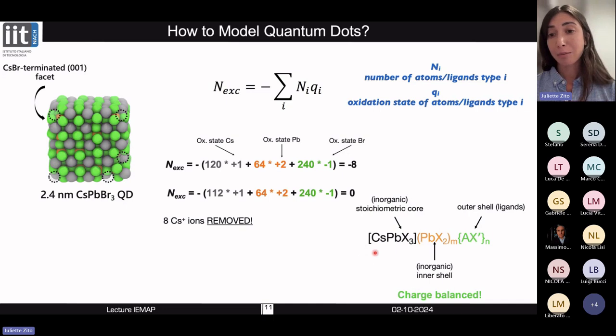and with our final quantum dot model that can be written as made of an inorganic stoichiometric core with an inner shell, surface shell, which is still inorganic, and then an outer surface shell, which in our model is inorganic, so A is cesium and X is bromide. But in the experiments, A can be a cationic ligand, such as ammonium ligands, and X can be anionic ligands, such as oleate ligands, for example.